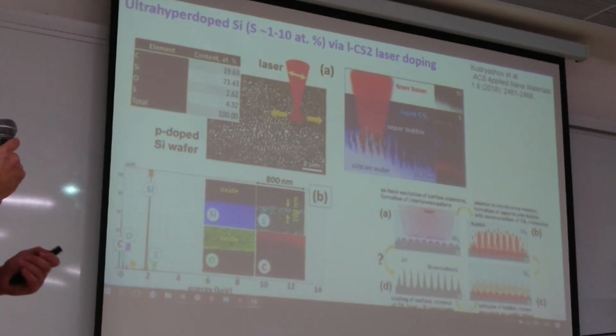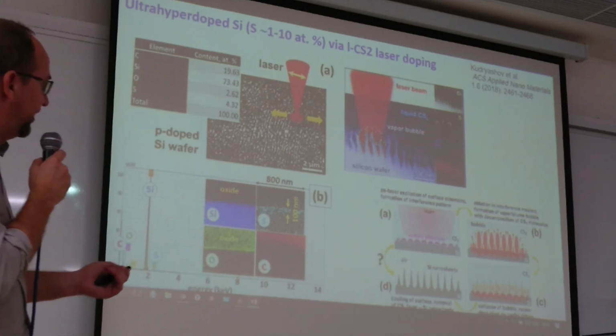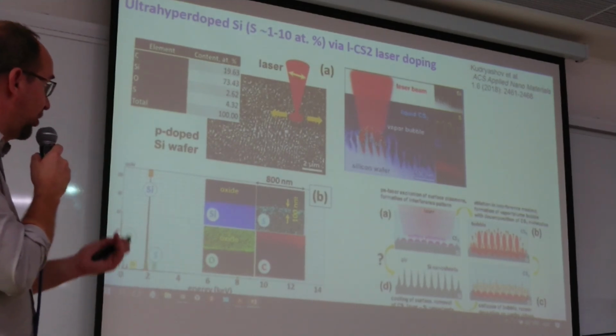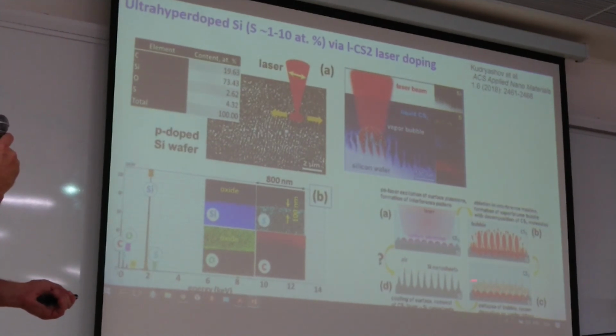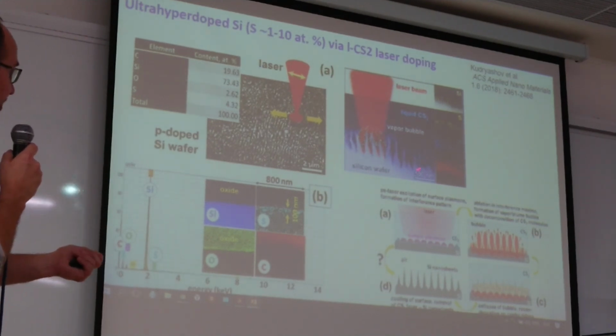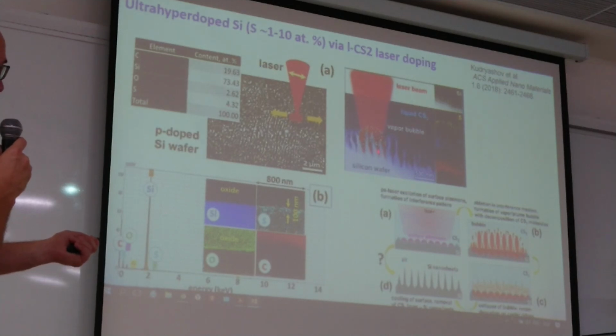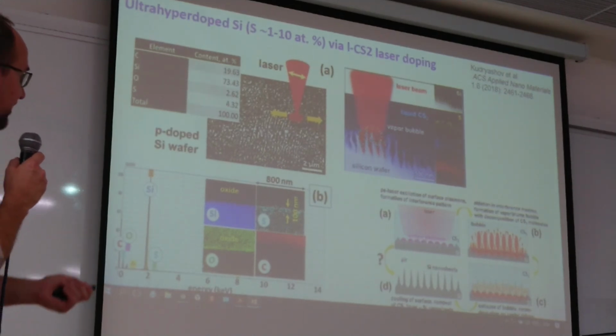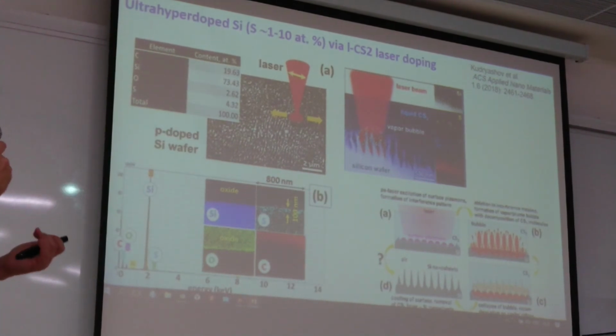Again, if you look at TEM pictures of these spikes, they are significantly amorphous, because this kind of laser technology assumes redeposition of silicon ablated from valleys onto these spikes. So we need annealing again, and we choose the right temperature for annealing to convert amorphous silicon to crystalline silicon, but simultaneously produce the right state of sulfur centers.